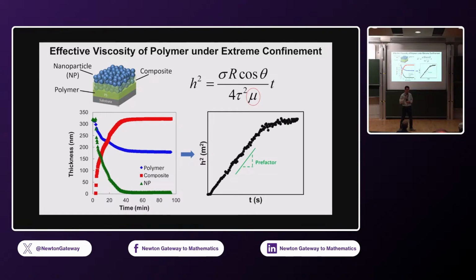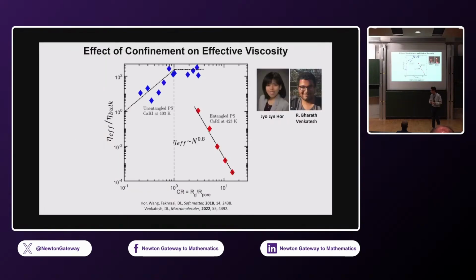Okay, so that's what we do to measure the effective viscosity of this polymer going through this capillary infiltration, and then we compare that to the bulk melt state viscosity of the same polymer at the same temperature. So here's the result. I showed this one plot, but this is really the results of 2 PhD theses. Okay, these 2 students. So I have 2 different cases here. Again, this is the effective viscosity that I got from Lucas-Washburn. That's the bulk viscosity in the melt state at the same temperature. And this is the confinement ratio between the characteristic size of the polymer to that of the pore.